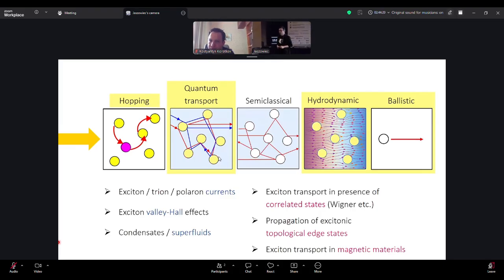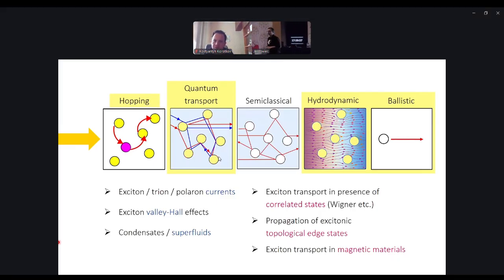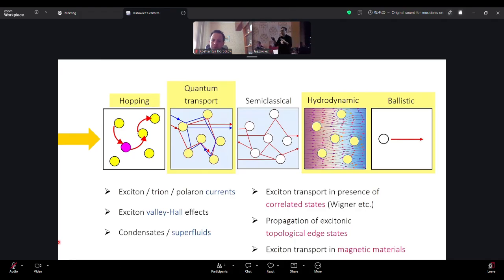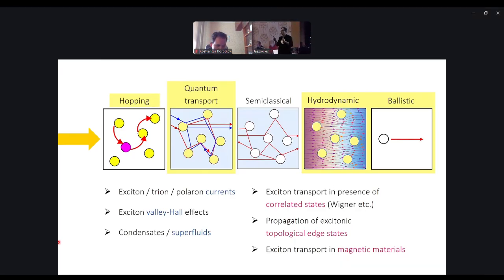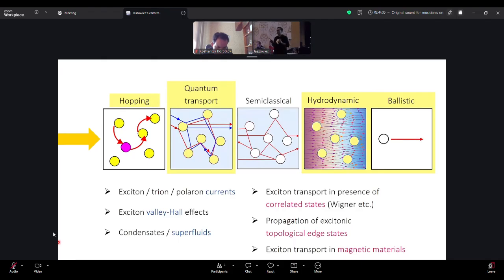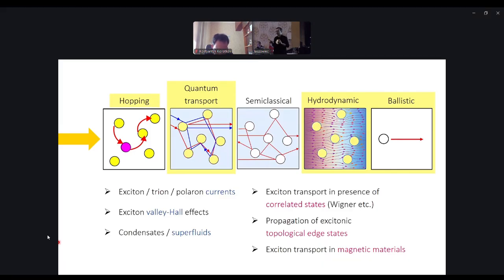The distance itself, in many cases, is determined, let's say if we talk about free diffusion, by the material quality, because realistically, the lifetime is what limits the distance. Looking at organic semiconductors, I didn't give those examples here, but it is also a very rich field. In tetracene, for example, people have shown that excitons can diffuse by many micrometers. It just happens over microseconds. So the transport is relatively slow, but they go far.